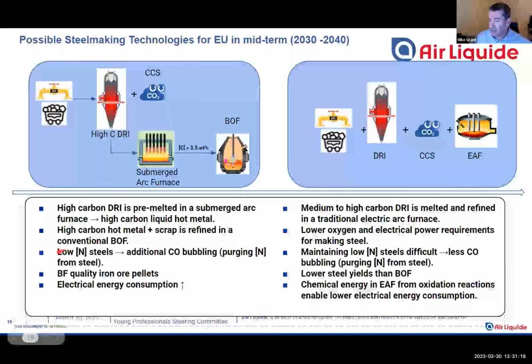And why do they want to do this? Well, one of the issues with producing low nitrogen steels is we rely on the CO bubbling to purge the nitrogen from the steel. And this is one of the important reasons why it's hoped that the BOF can be kept.